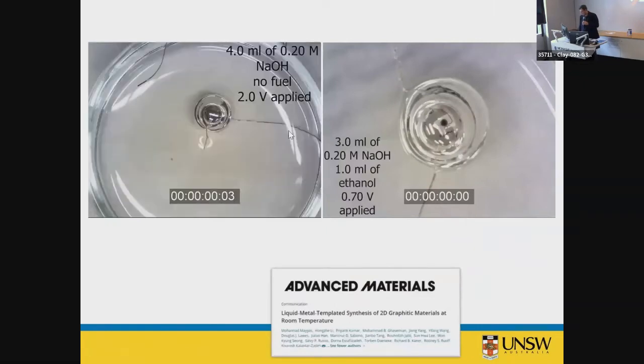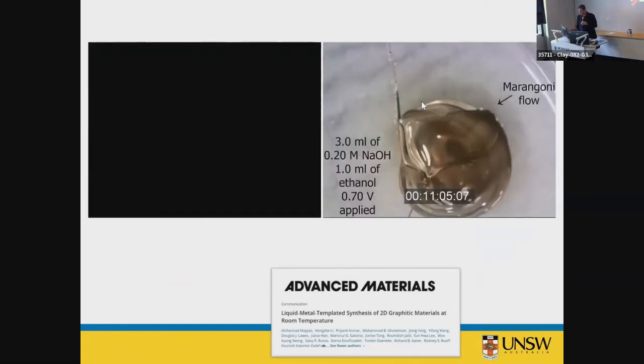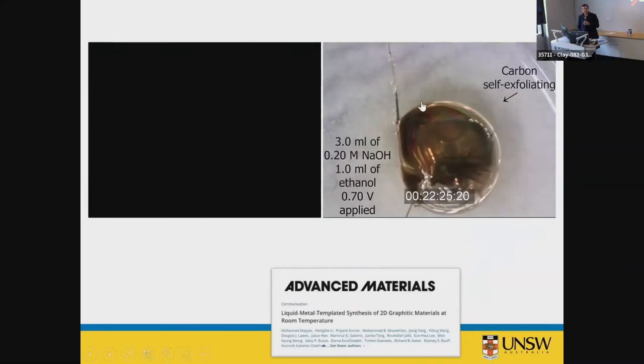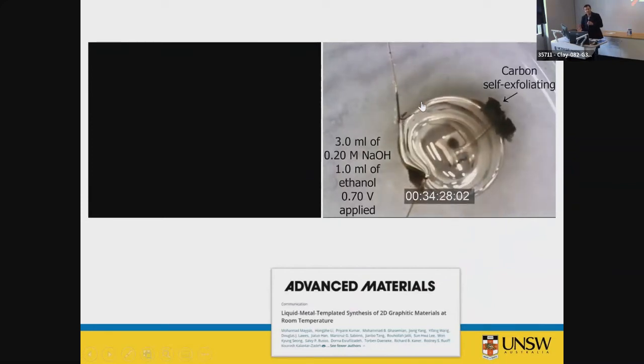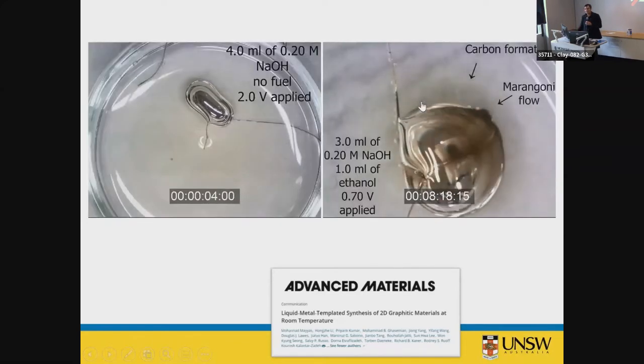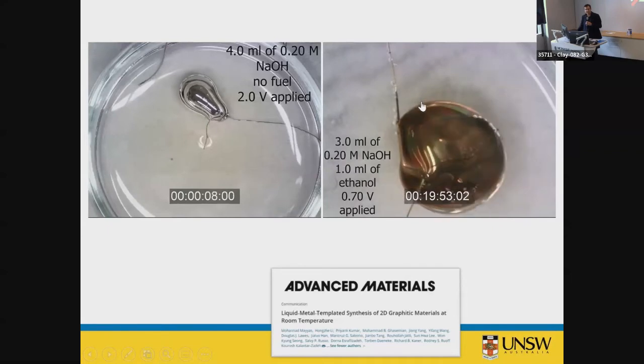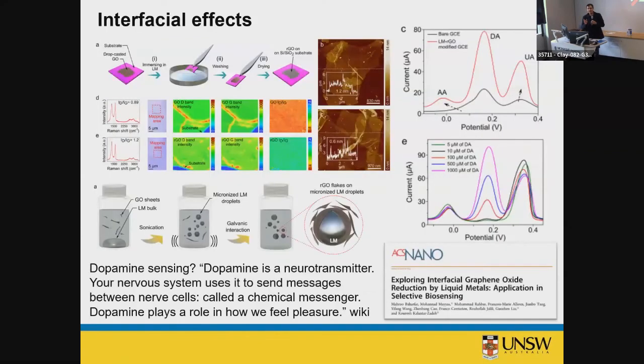If you don't have any of these precursors in the environment, the surface remains shiny after 10-20 minutes. And if you have these precursors, the surface becomes black and brown, depending on how much voltage you apply. You can make graphene oxide. If you have nitrogen in your precursors, it becomes nitrogen-doped, highly catalytic material, and the rest. And everything is done at room temperature.